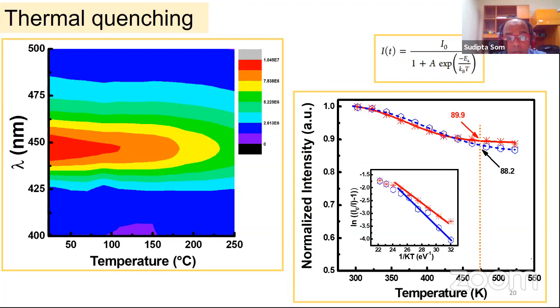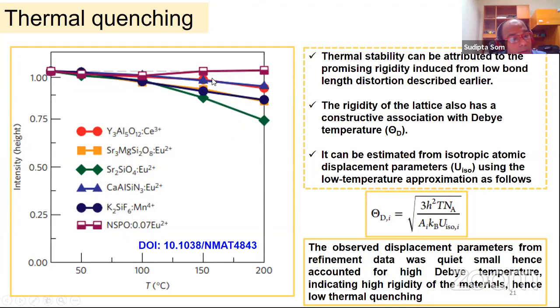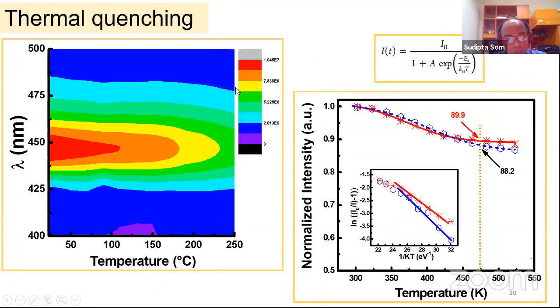Some commercially available materials I have shown in this slide, with their temperature dependent PL properties. You can see that only one kind of phosphor has zero thermal quenching. For our case we didn't get zero thermal quenching, but we are getting a very highly stable material. Moreover, we can use the Arrhenius equation to calculate the activation energy from this formula, and that activation energy also tells about the thermal stability. In our case, we are getting about 0.35 or 0.31 electron volt, which is way larger than the commercially available phosphors. So from here, we are sieving out those materials which are thermally stable.